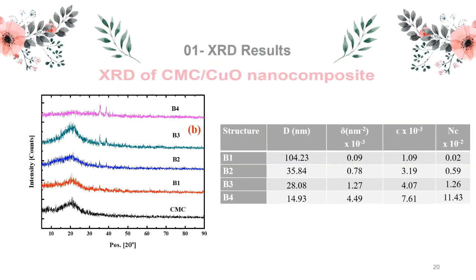This figure presents the XRD pattern of CMC and CMC doped with different concentrations of copper oxide nanoparticles. It can be seen from the figure that CMC and CMC nanocomposite films have a broad peak near 2 theta equal 20 degrees due to the amorphous nature of the CMC.